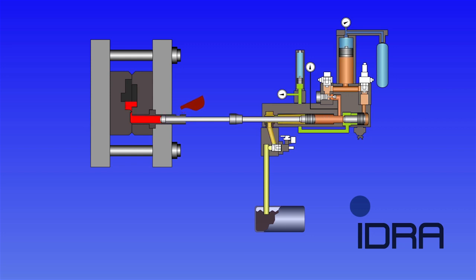After the metal has reached the gate of the die's runner system we accelerate the piston to fill the cavity of the die. The nitrogen in the accumulator has the energy stored from the machine pumps and we can release this in a controlled way to give a high speed injection to give short fill times often required in high pressure die casting.